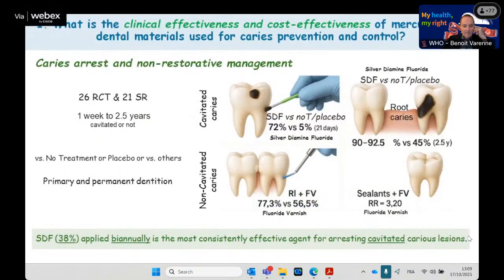Regarding caries arrest and non-restorative treatments, we included 26 randomized controlled trials and 21 systematic reviews, covering both primary and permanent teeth. The data show that 38% silver diamine fluoride applied twice a year is the most consistently effective agent for arresting cavitated carious lesions and root caries. In addition, 5% fluoride varnish, whether used alone or in combination with a sealant or an infiltrating resin, is effective in arresting non-cavitated carious lesions.